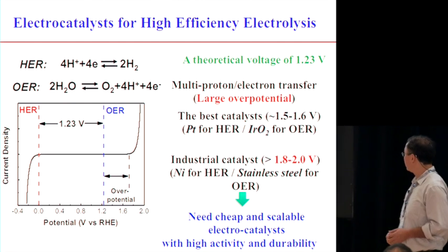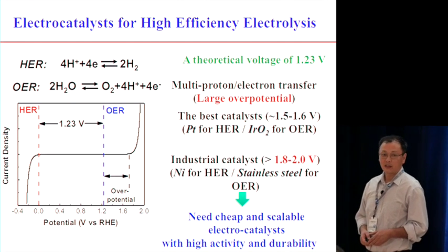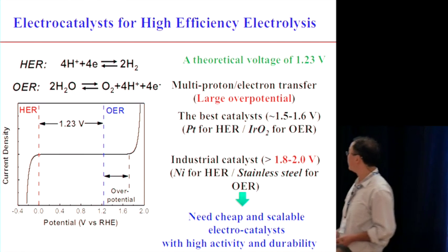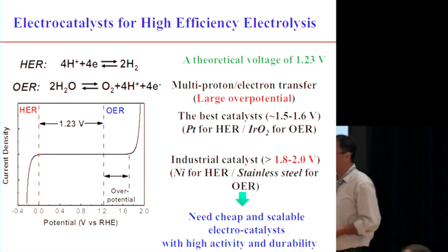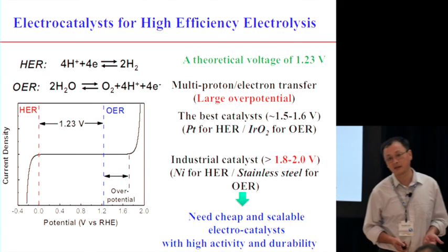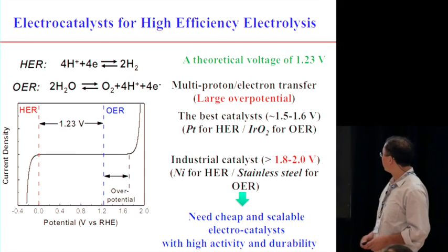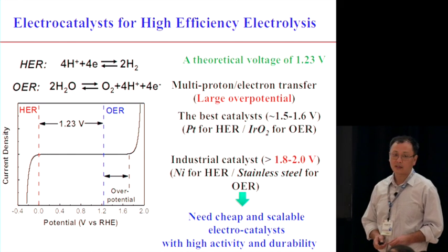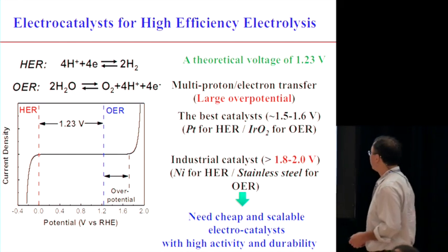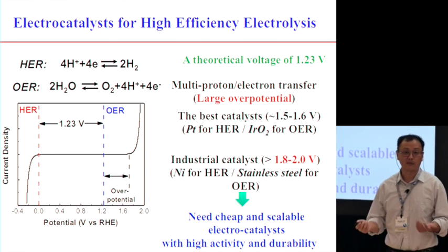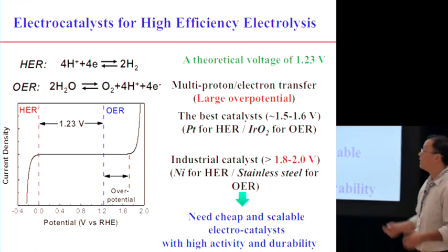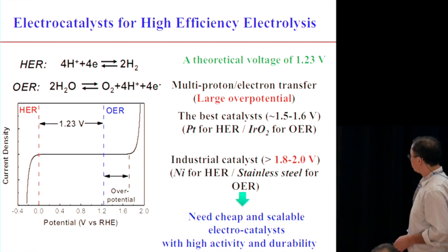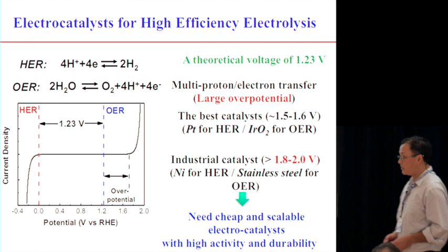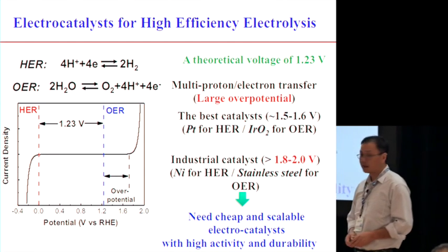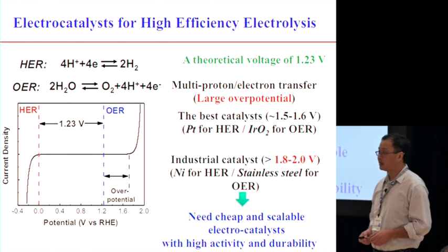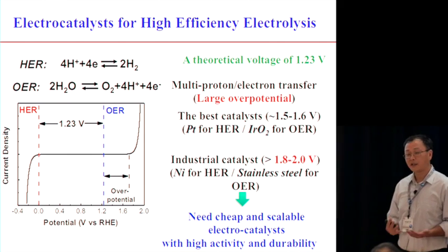cost, typically the catalyst for HER is nickel. Nickel is very abundant and low cost. And then the electrode for oxygen is stainless steel, which is also quite abundant and low cost. But the caveat is that activity is quite limited. So you would need a high voltage, like 1.8 or even 2.2, 2.3 volts, in order to have large amounts of hydrogen and oxygen. So we would like to have cheap and scalable catalysts, so that you can get water to split at very high energy efficiency.